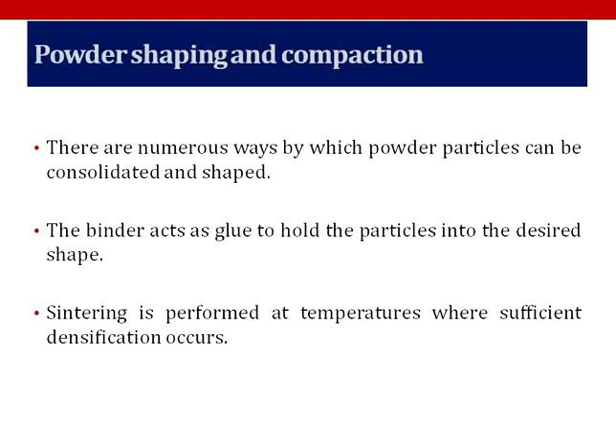Now, an alternative is to use low pressures and high binder content to shape the powder particles. The binder acts as a glue to hold the particles into the desired shape. Most binders are polymers, which might be mineral oil or polyethylene. In shaping, the porosity ranges from 40% to 60%, excluding the polymer. Therefore, sintering is performed at temperatures where sufficient densification occurs. Fine powders assist in densification during sintering.